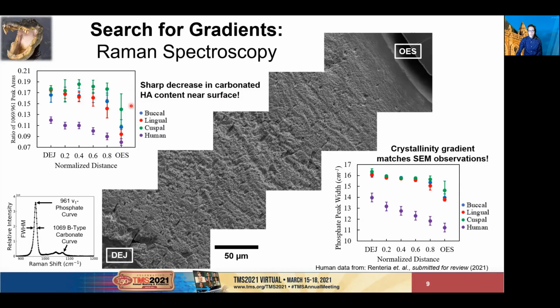The other measurement we got from Raman was the full width at half max of the phosphate peak, which reflects the degree of crystallinity. A more pure and fully crystallized sample would have a narrow peak, thus a broad peak should reflect a lower crystallinity, for example, caused by higher organic protein content or gaps between the columnar units. Again, the measurements line up well with the microscopy and the nanoindentation gradients.